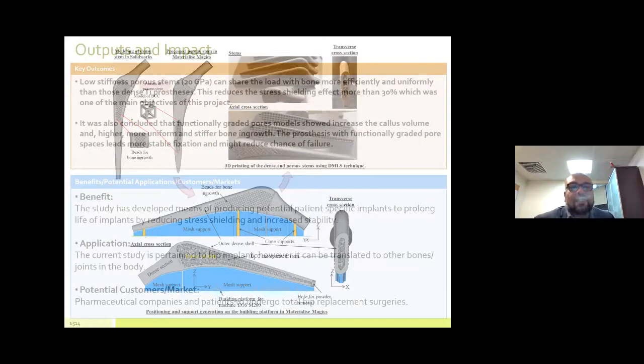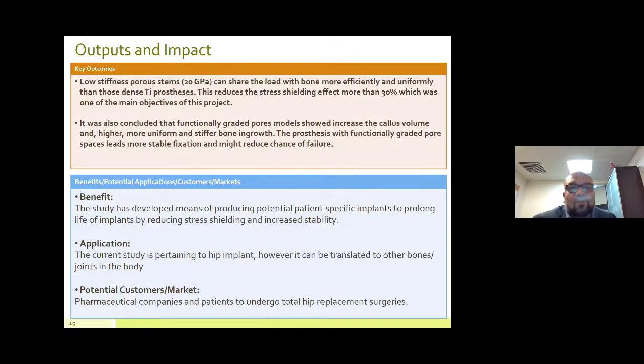The output is we managed to achieve a low porous stem of 20 gigapascal, quite close to the stiffness of the femur bone. And we managed to reduce the stress shielding by 30%. So most of our targets in the project were achieved. Also, with our new approach in the algorithm for stability, we have proven that we can enhance the bone growth along the stem by designing certain pores on the outer part of the implant.